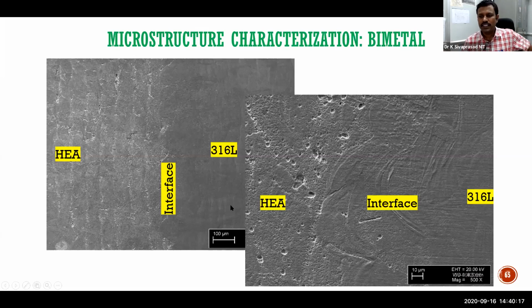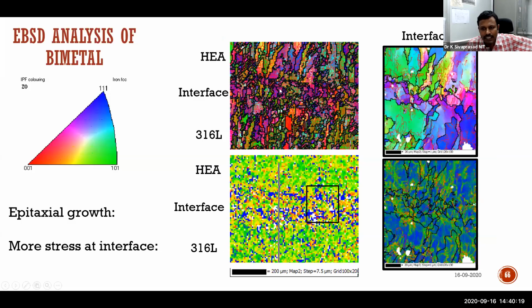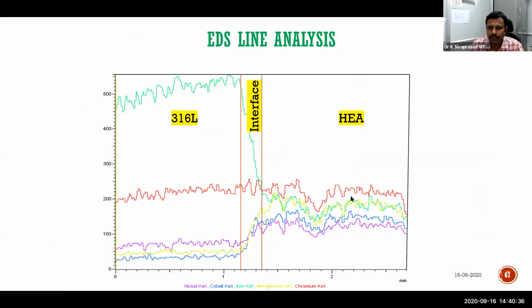And EBSD studies based on orientation imaging microscopy clearly evidence that it has a very small interface region that is also not too much deviated. So the interface is really very good, what we'll call an intact interface. And the elemental mapping that we have taken shows a gradual variation from one end to the other.